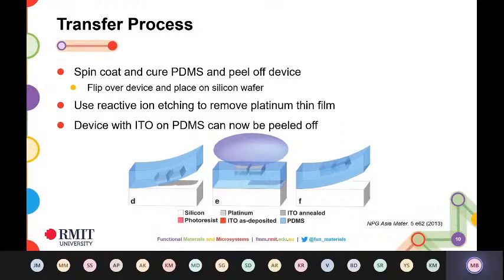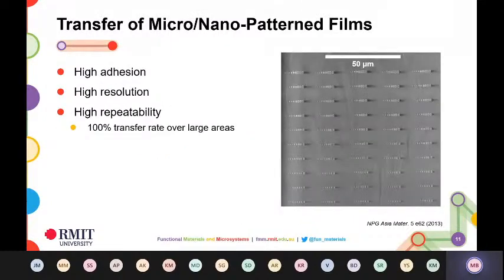We were really happy with this. We thought we'll do a little more research. We'll understand what the parameters are. We tried a few different thicknesses. We tried micro patterning them, nano patterning them using electron beam lithography. It worked every single time. So getting a large transfer rate over a very large area, like a 4-inch diameter silicon wafer, was possible every single time. And because the oxide is semi-embedded inside the polymer, you have very high adhesion. So you don't have this flaking off or cracking off. It is pretty much set quite well within the polymer.